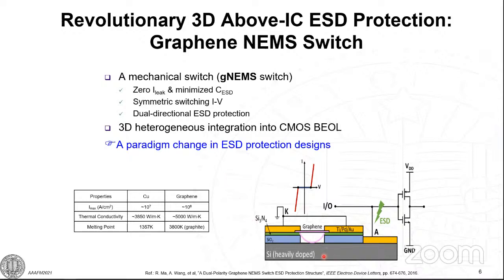Another very nice feature is that the graphene gNEMS device is not inside silicon. It's actually placed on top of the silicon in the so-called back end of line, BEOL, deck, where you have the complex metal interconnect for the IC. So this is another major feature. That means the graphene ESD structure will not consume silicon area. Of course, because it's outside the silicon area, it will not introduce a lot of PN junction-based parasitic effects like noise, leakage, parasitic capacitance, and so on and so forth.